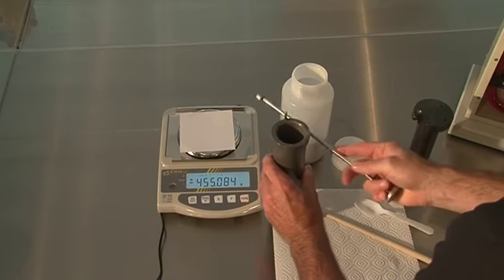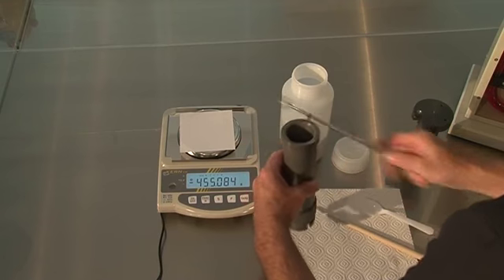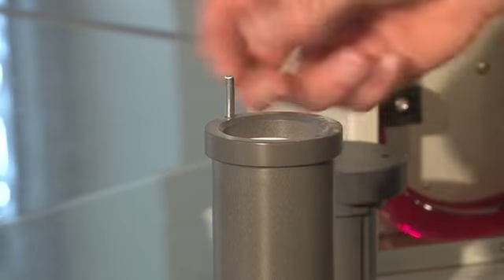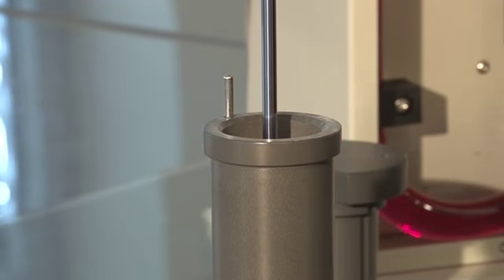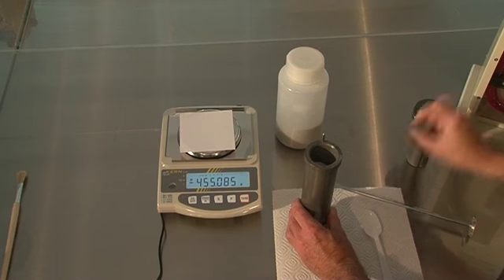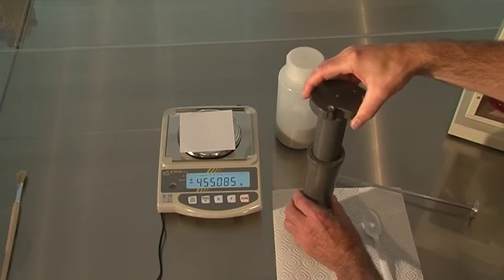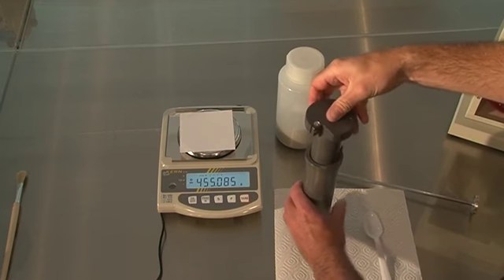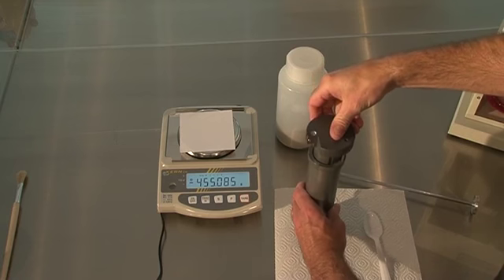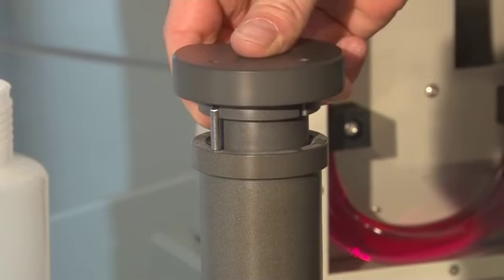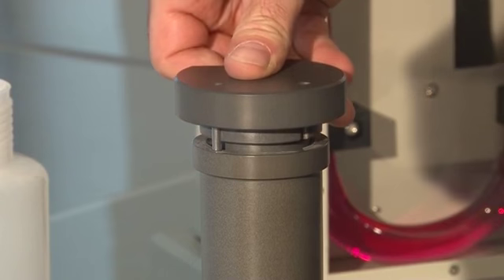Level the surface of the cement by gently tapping the measuring cell. Then place another filter paper disc and press it down with the tamper. Compact the bed slowly and continuously with the plunger until, by exerting slight pressure, the lower face of the cup is in contact with the upper edge of the measuring cell.